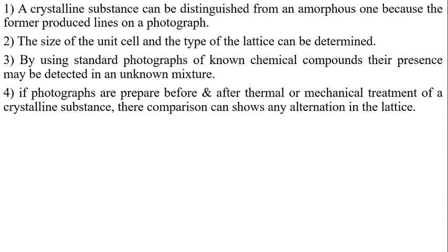The size of the unit cell and the type of lattice can be determined by using standard photographs of known chemical compounds, and their presence may be detected in an unknown mixture. If photographs are prepared before and after thermal or mechanical treatment of a crystalline substance, their comparison can show any alteration in the lattice. Thank you.